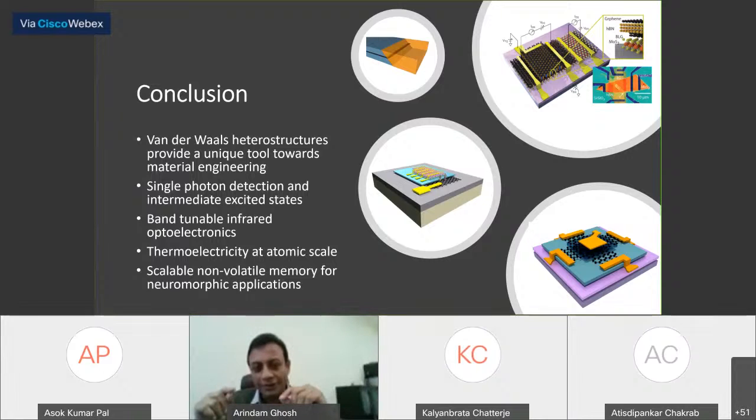You see, the problem is, in the same material, the moment you have a band gap, which is necessary to absorb light, you cannot get high electrical mobility, because the disorder becomes very strong and it scatters electrons as they try to go through.